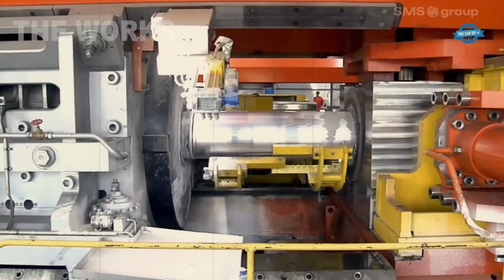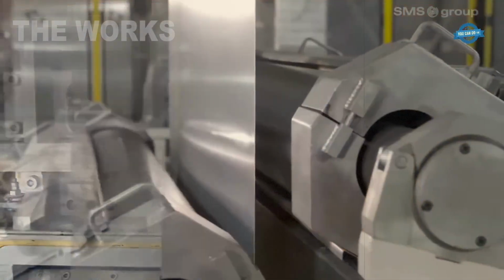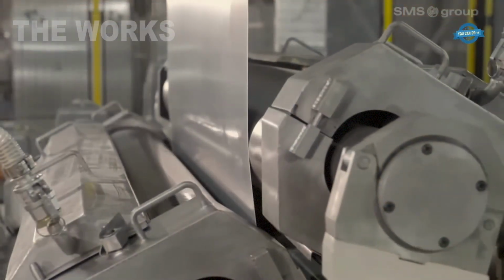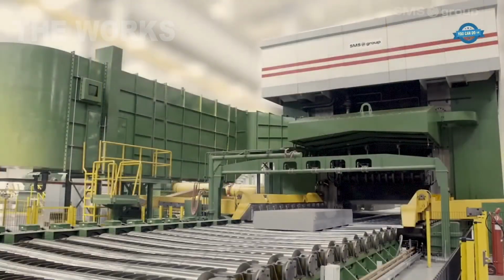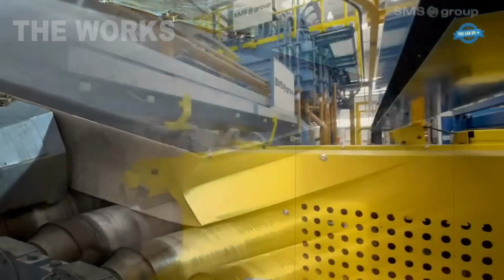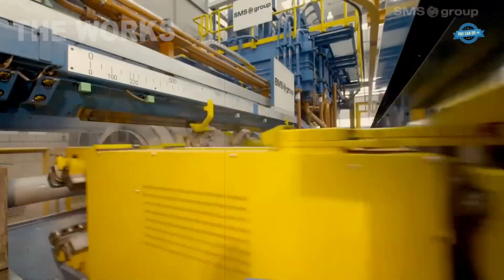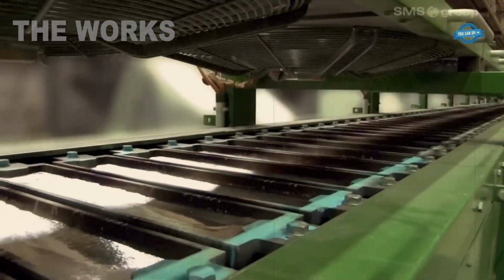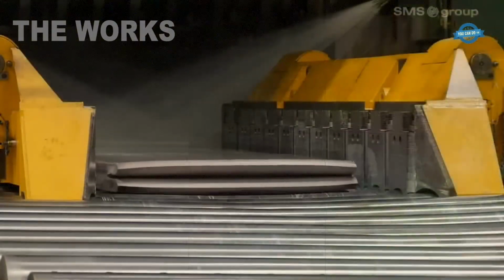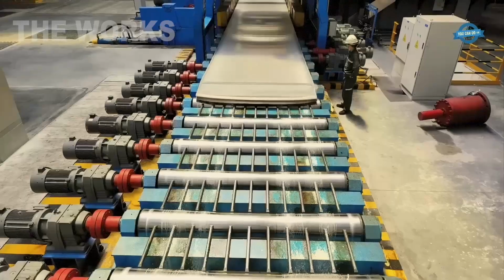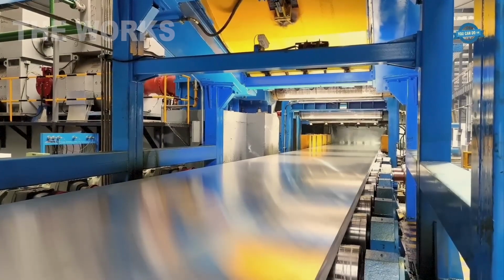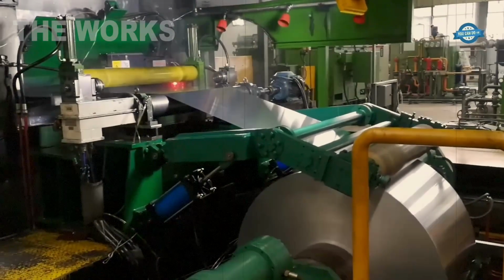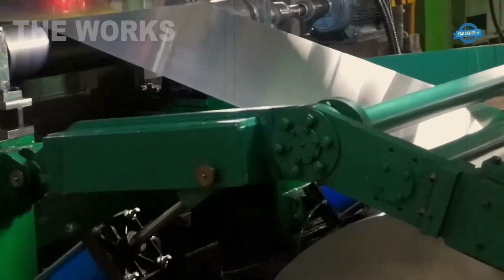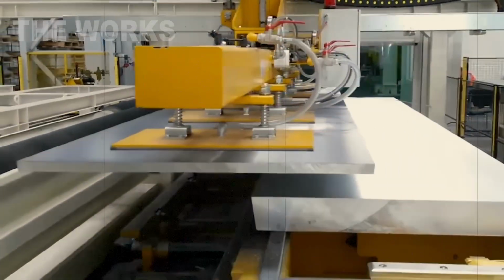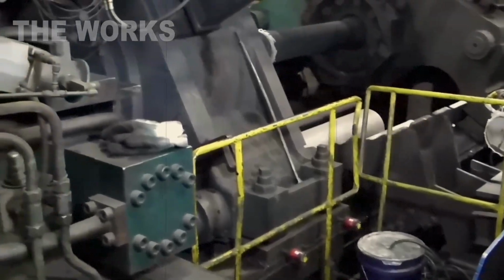After extraction from molds, aluminum ingots are moved to a preheating furnace to soften them, bringing the metal to ideal condition for rolling. Once the ingot is ready, it passes through a set of counter-rotating steel rollers where enormous pressure flattens and elongates the aluminum block. This process repeats across several rolling mills, with the gap between each pair gradually decreasing. As a result, the ingot, initially several centimeters thick, gradually transforms into a thin, uniform metal sheet. By the final stage, the sheet reaches its target thickness, often to several hundredths of a millimeter, and moves forward as a continuous strip, then is tightly wound into large coils.